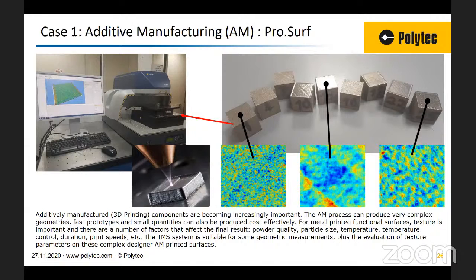And for this specific image, you can see that these are all measured and imaged with the ProSurf product. If you think about AM surfaces, you're normally taking something like a 20 micron ball, sticking it on a surface, melting it. So the digital sampling of a ProSurf starts from 14 microns. So you can see it's quite well matched to the smallest types of features you may want to see in terms of texture representation.